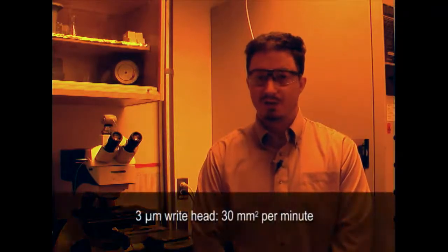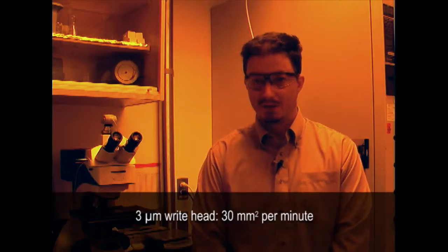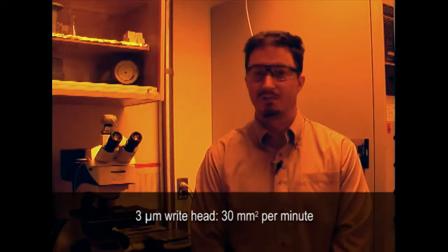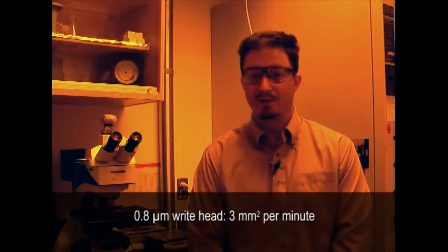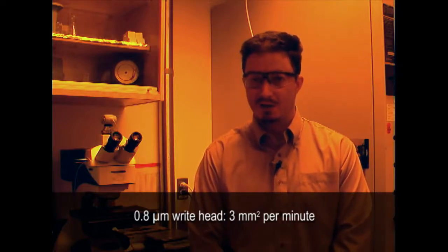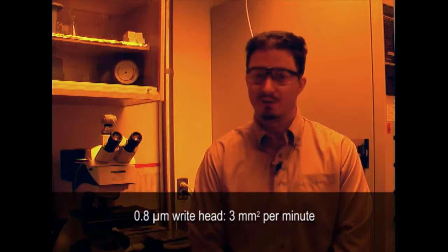So when our MicroPG is ordered, we have several options. We've chosen to select the 375 nanometer laser over the 405 so we can work directly with UV polymers, including SU8. In addition, we've chosen the 3 micron write head as it writes at the relatively quick 30 square millimeters a minute. The 0.8 micron write head is an option, however the write speed decreases to 3 square millimeters a minute. A chrome-on glass mask takes between 4 and 6 hours at full speed on my machine. On the higher resolution tool, that would take in excess of a day.